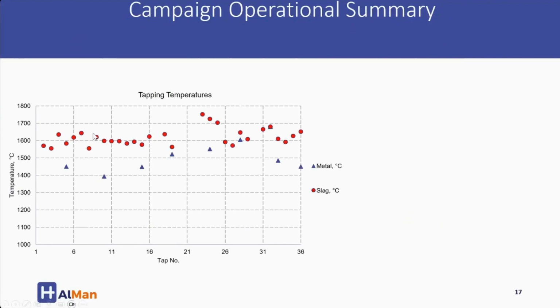For the slag smelting section, taps 1 to 20, our target temperatures were 1500 to 1600 degrees Celsius, and as you can see, we were close to our target temperatures. For the smelting of pre-reduced material, our target temperatures were above 1600 to 1650. As you can see, we are also close - we are very high there - and that's why we had to adjust the SCR a bit so we don't superheat the slag metal.